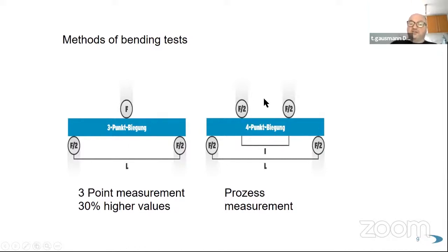The better the material is produced, the more homogeneous it is, the fewer cracks you get here and the higher the values go here. But for sure, since you've got lots more possibilities for a crack, a 3-point measurement is always roughly 30% higher in value than a 4-point measurement. This is something you have to keep in mind. A 3-point measurement is the lowest possible method under norm 6872 to measure the material.